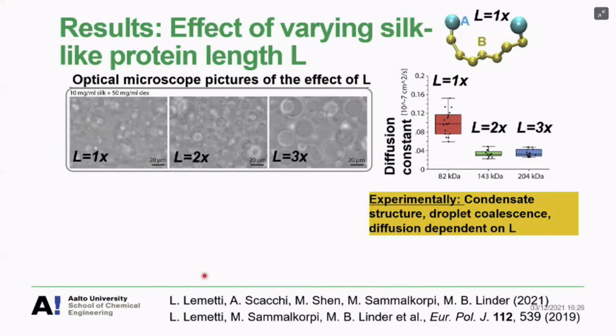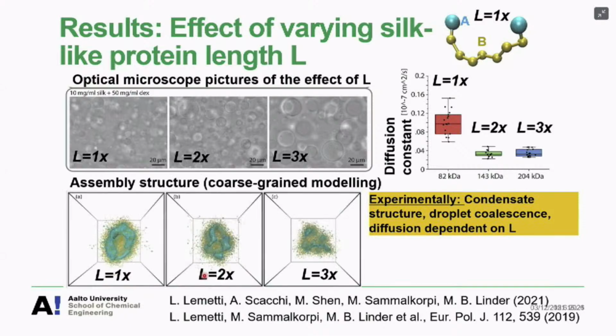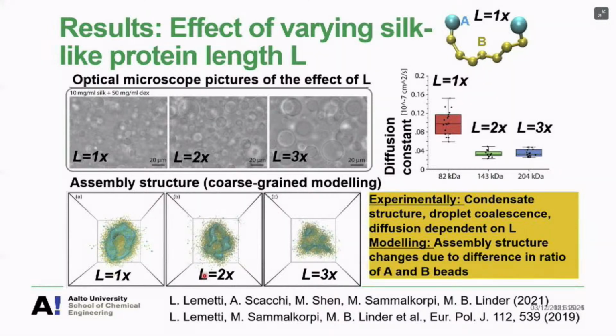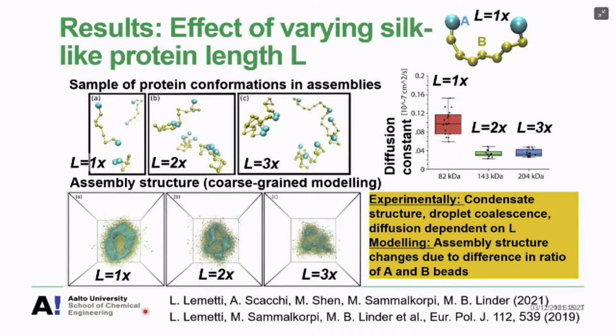So we used the Brownian dynamics model for this computationally, and the assembly structures are here. What you should be seeing there is that the assembly structure is actually changing quite a bit due to the difference in the ratio of the A and B beads. For the short one, it forms uniform domains that are connected, and going longer, it's not any more connected in terms of end unit beads. It's more fractionated. And this can also be seen in the conformations of the proteins. What we have there are pairwise connections in different amounts between those strongly attractive end units, depending on the chain length. And that changes the conformations.